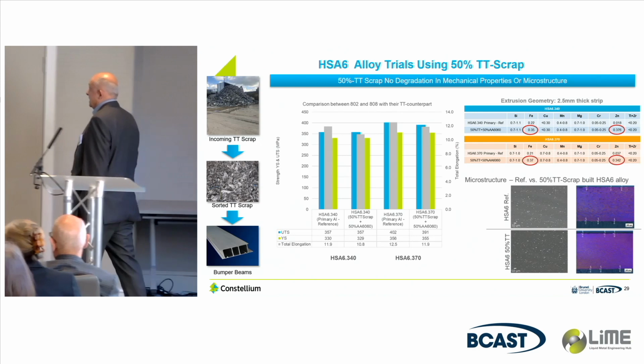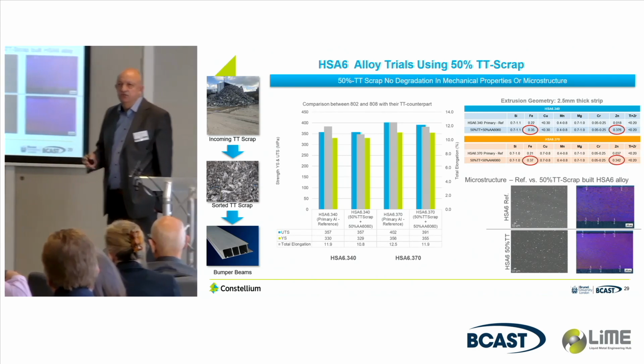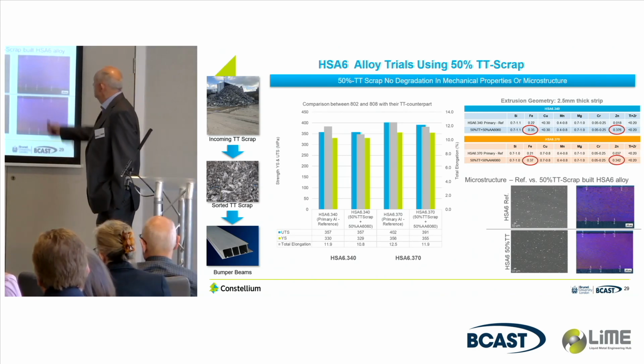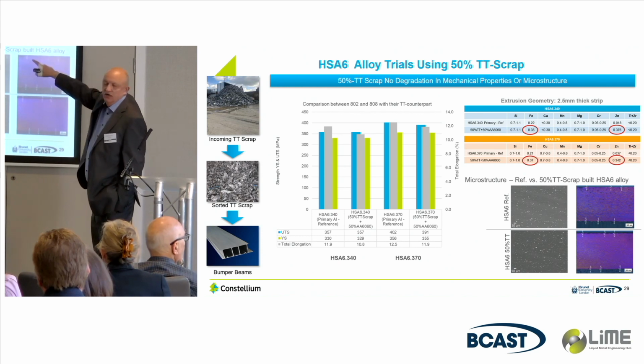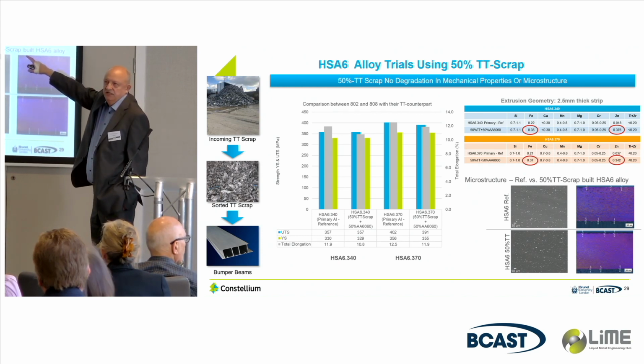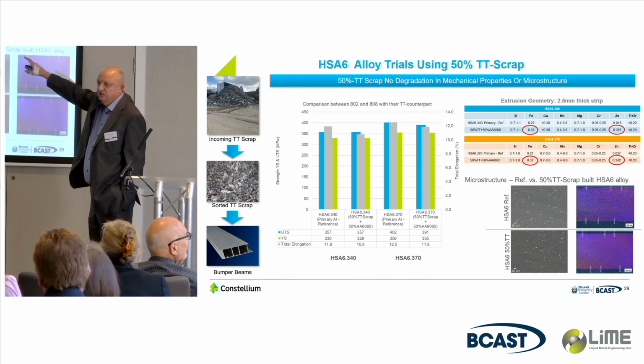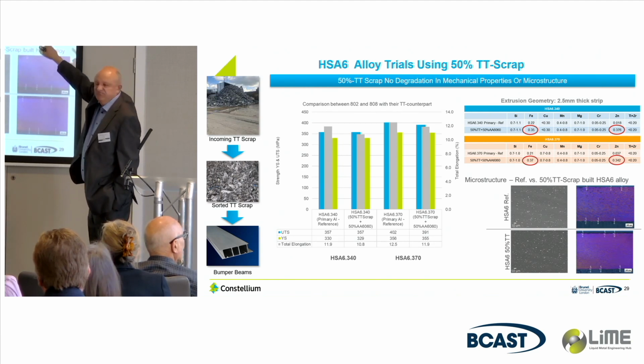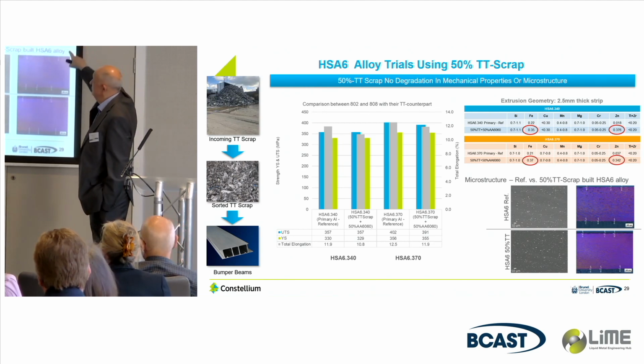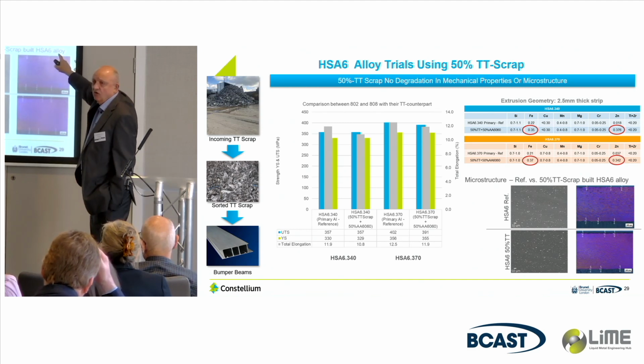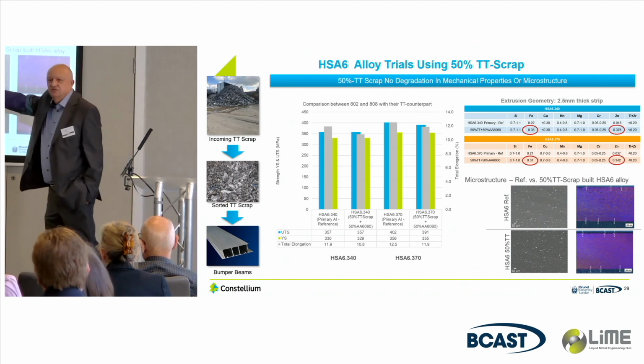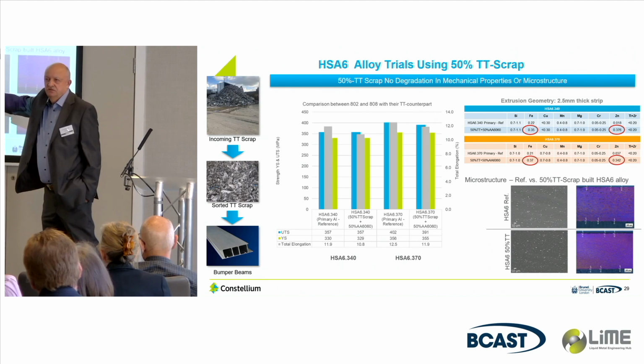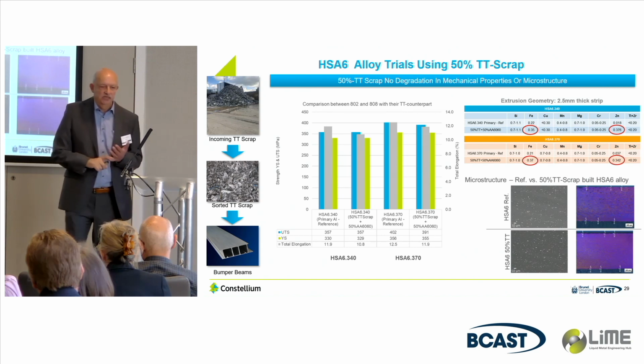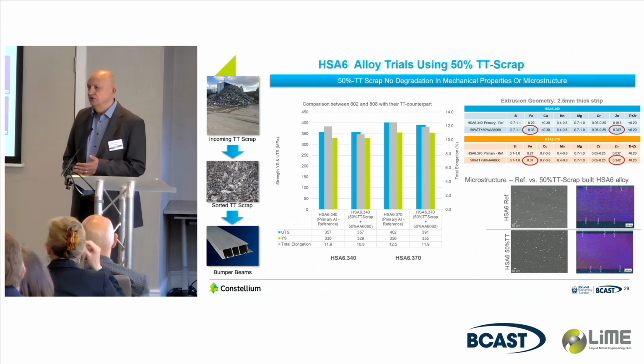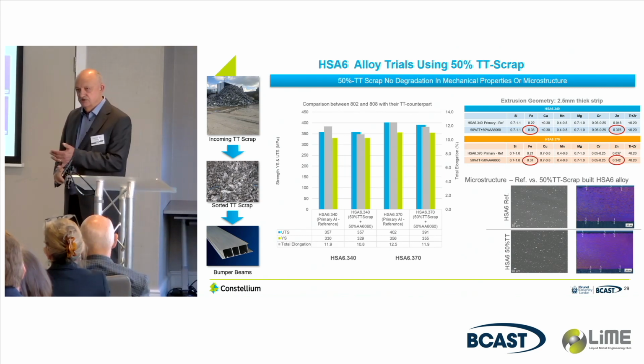And this is just a very quick example. We've got many more actually. But even when we get to relatively high iron levels, typically in these materials you're probably talking about 0.2, 0.22, so we're roughly double. We've got relatively high levels of zinc, which is a common impurity. It's really having no difference at all to the mechanical performance and mechanical properties of the material. We've also been able to show, from a corrosion point of view, it's having no difference on corrosion either.